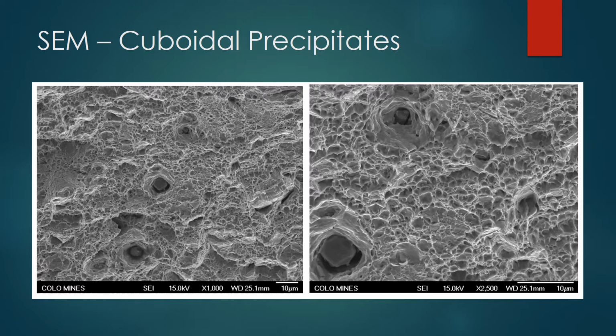So in both types of samples, we observed cuboidal-shaped precipitates to a much greater extent in the machine samples compared to the additively manufactured samples. In both cases, however, we did observe these cuboidal precipitates, and based on the very distinct morphology and the fact that other studies have found that 17-4 PH stainless steel, which is the material that we were looking at, when treated at the H900 specification, form BCC copper precipitates. So we believe that based on this distinct morphology and our experimental protocol, that these are indeed those BCC copper precipitates.